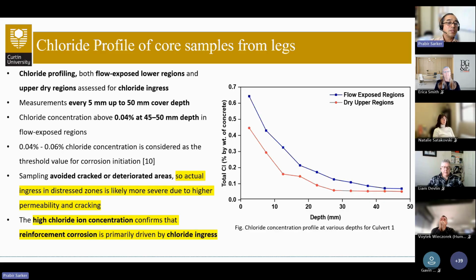It was tested at every 5 millimeter depth of the concrete, and what we see from this graph is two lines. The red line is from the dry upper region of the culvert legs, and the blue line is from the flow exposed regions. You can see the upper region has less chloride compared to the lower region, because the lower region was subjected to alternate wet and dry cycles of water carrying high salt contents.